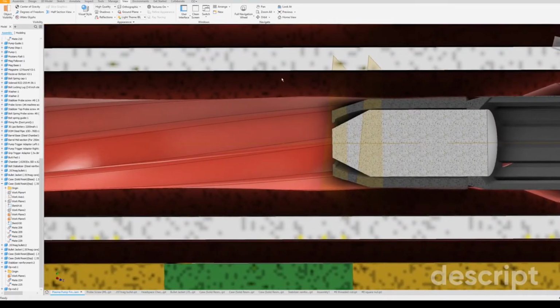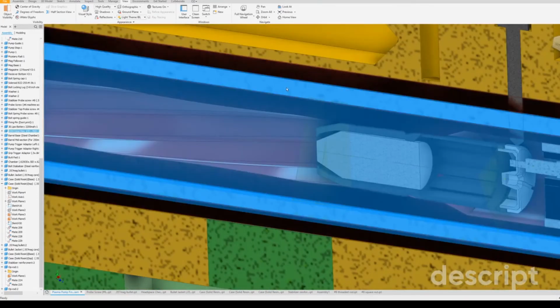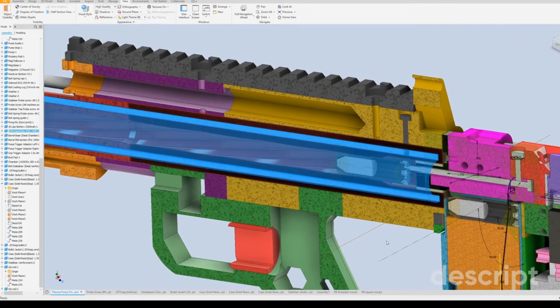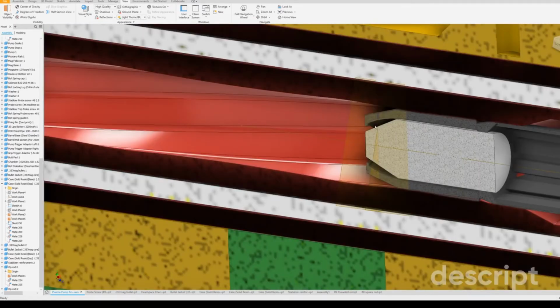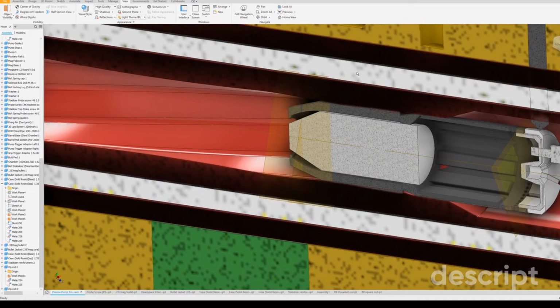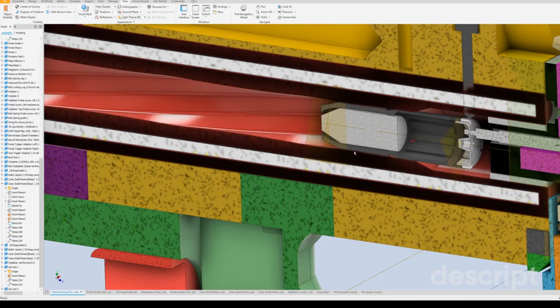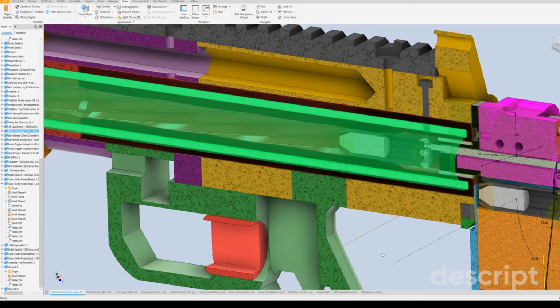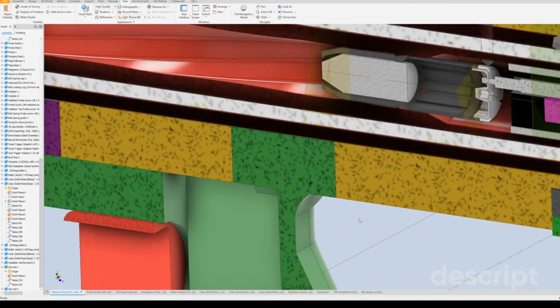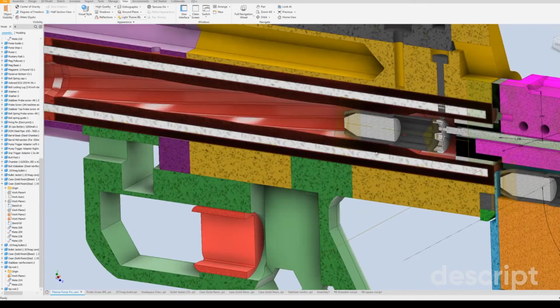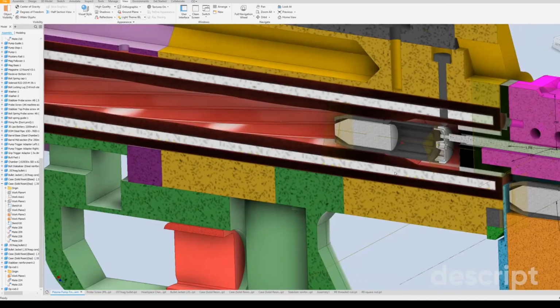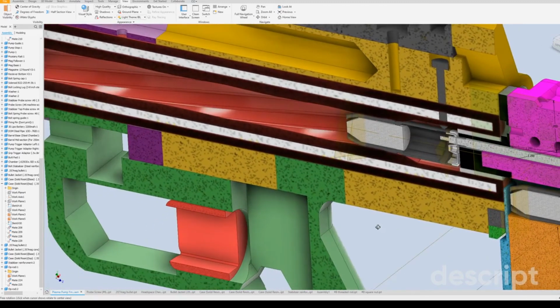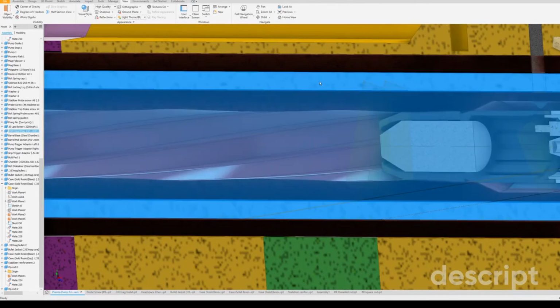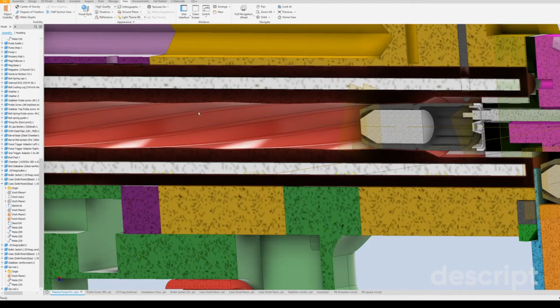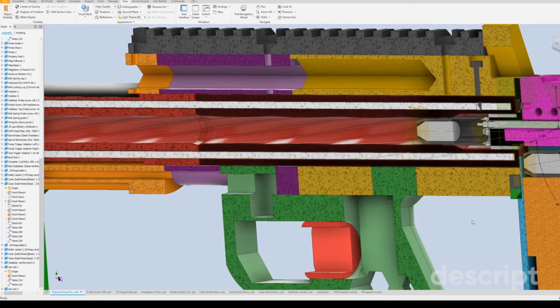So let's see. The rifling in the barrel is 3D printed, and it has a steel reinforcement tube around it. That basically compresses the rifling, or I should say, when it fires, the rifling is going to try to expand and it'll hit up against the steel reinforcement, and that'll compress it. That compression is a lot stronger than trying to pull a material apart, which is tensile strength. The compression strength of a material is usually much higher than the tensile strength. So this utilizes that compressive strength in the barrel. The manufacturers don't really give out the compressive strength, so that's something that I'm going to be doing research on with my school next semester to hopefully get some solid values. But as it stands right now, the value should be lower than the pressure value that the steel pipe bursts at, so the rifling should shatter and release pressure before the steel pipe bursts.